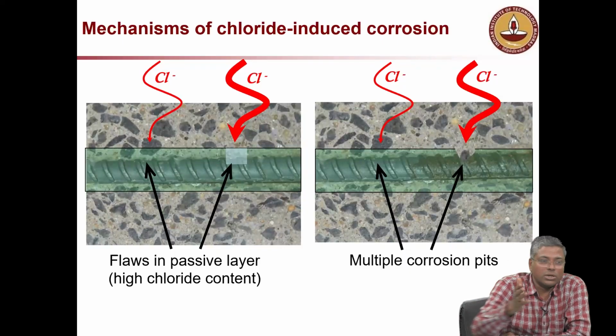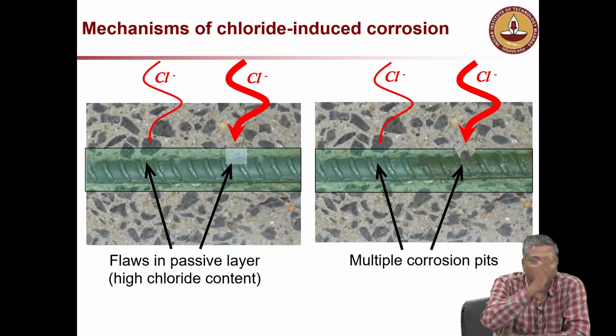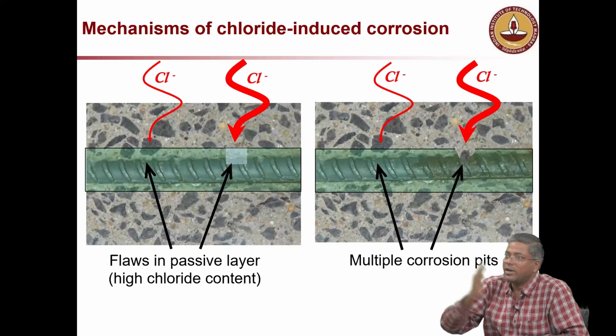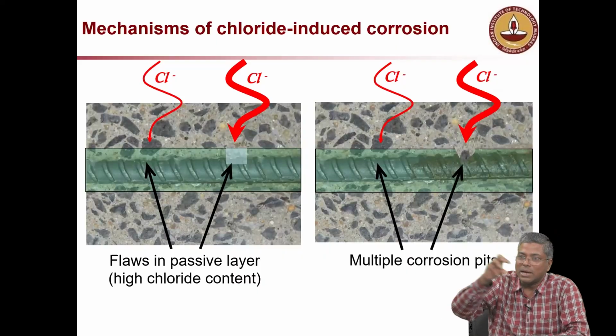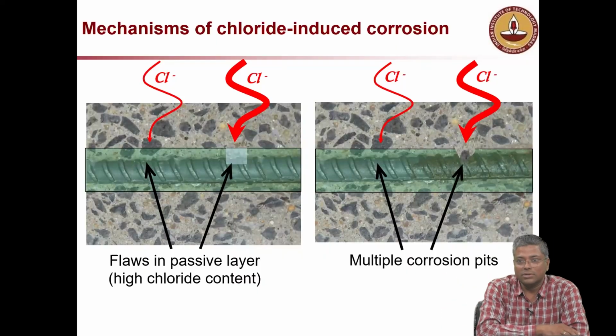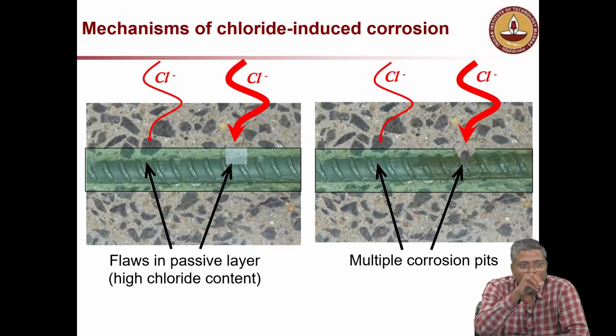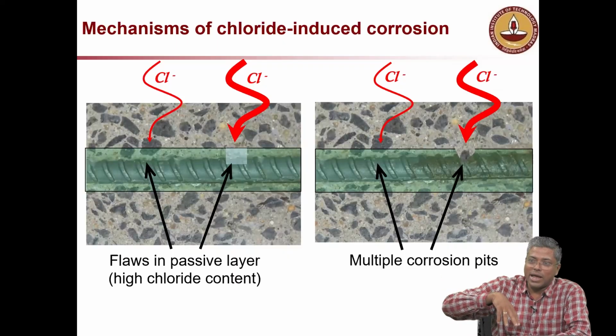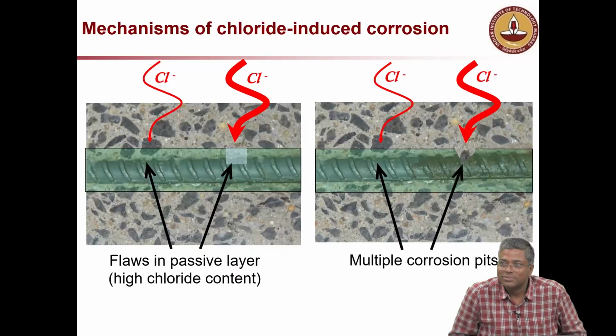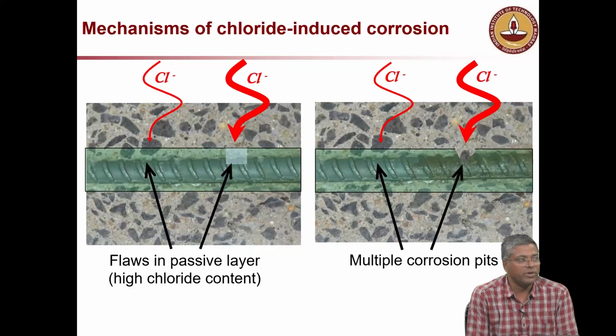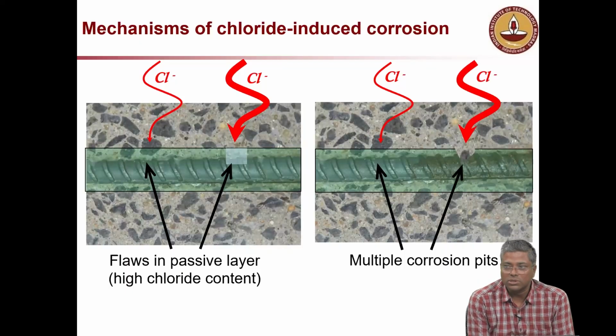Because it is not a straight line, the speed of chloride penetration is different at different locations. So at some points you'll get more chloride than at others. The first point where you get more chloride than the others will start corroding. So that's why you have preferential corrosion in the case of chloride induced corrosion.